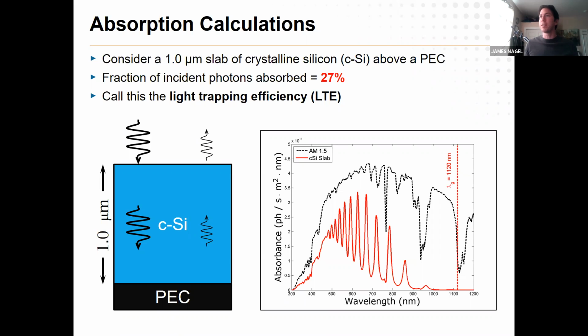So this is all closed form calculations on this model, and we're assuming a perfect reflector at the bottom. So that's perfect electrical conductor. So no loss in the bottom contact here, and illuminating it from the top at normal incidence. So the question then is, all things being equal, how much light will physically be absorbed in this kind of system? So what happens is, you shine light, I get a little bit of a reflection. Some of it transmits through, bounces back. Some of it then transmits out again, and some of it will bounce back and forth, and you repeat forever to get some net absorption on this thing. So here, this dashed curve here, this represents our sunlight. You notice, again, it's photons per second per square meter.